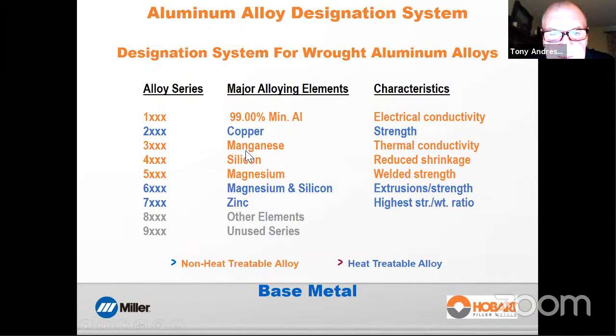3000 series, manganese. Thermal conductivity is really good. It has the highest thermal conductivity after the 1000 series, and it's used for things like pots and pans. The old aluminum pots and pans were all made of 3000 series. Radiators and heat exchangers, because of its good thermal conductivity and relatively moderate strength, use the 3000 series. 4000 series, silicon. Where do we see them? Filler alloys. Why? Reduced shrinkage. Silicon has some really strange characteristics when it's in aluminum. One of them is that it actually expands when the material solidifies rather than contracts. So it is a really good element to have in a filler alloy to prevent hot cracking. So some of the lowest crack sensitive materials out there are 4000 series.